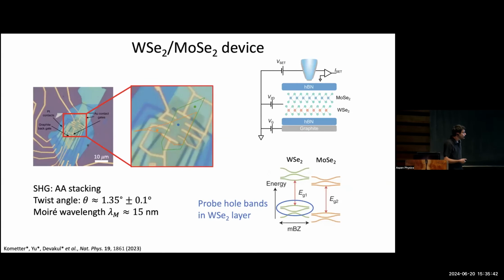Here's our sample. Maybe the zoom in is more useful. I'll just tell you a couple of critical aspects of it. So first of all, the twist angle is about 1.35 degrees. It corresponds to a Moiré wavelength of about 15 nanometers, so actually quite large compared to what people have traditionally studied in transition metal dichalcogenide systems.